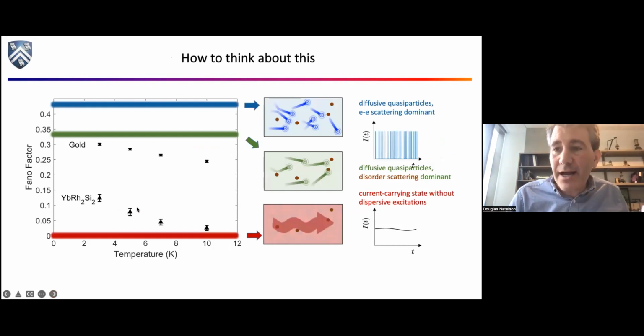So what do we think is going on? Here's the cartoon. Again, here's Fano factor versus temperature. Up here is that √3/4, and the picture there is that I've got quasiparticles scattering off of each other more often than they scatter off the dirt, and the dirt is represented by these dark brown dots. That's in the gold. And then here's the 1/3 Fano factor. That's the case where the scattering off the dirt is the dominant thing. But in both of these cases, the current is carried by these well-defined objects, these quasiparticles. The current is a function of time. You can basically look at the discrete arrivals of the particles, and that's what gives you the shot noise.